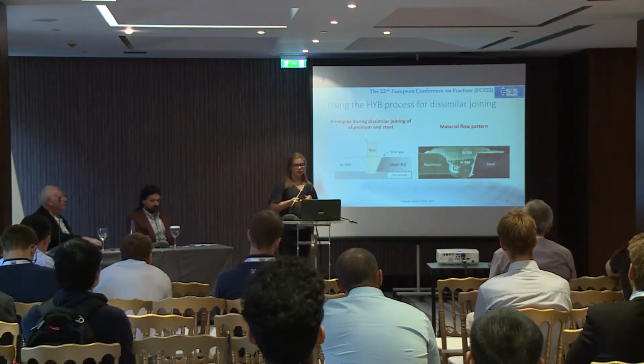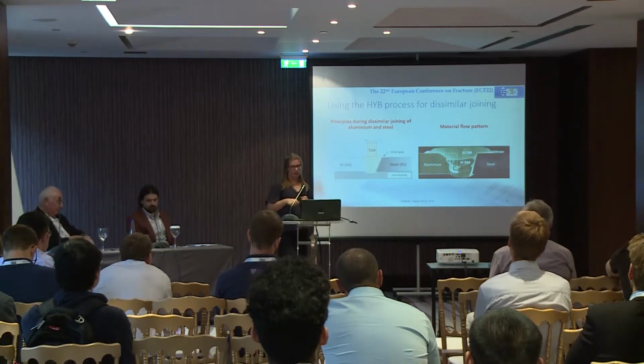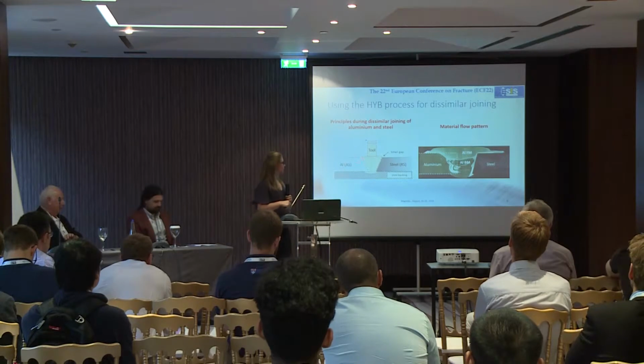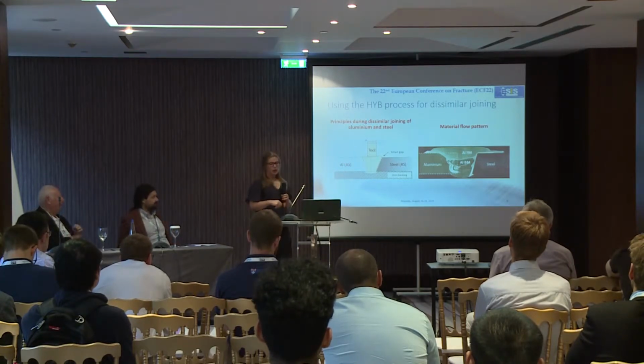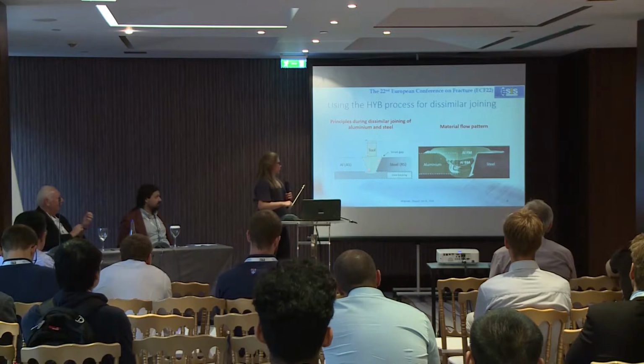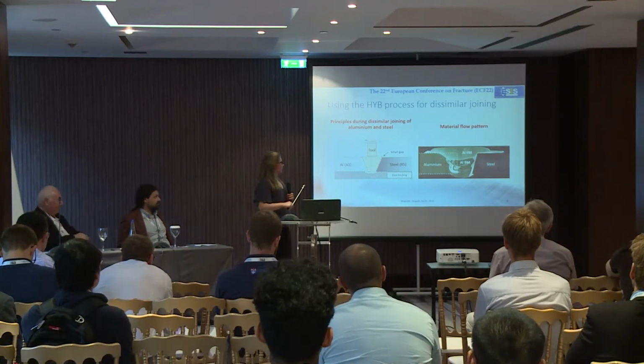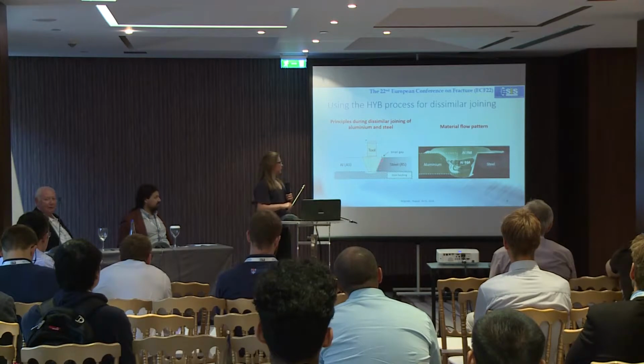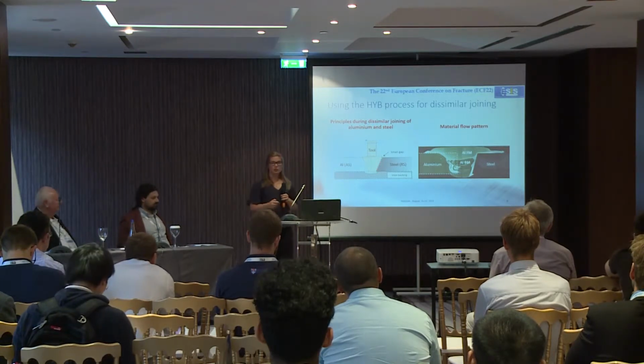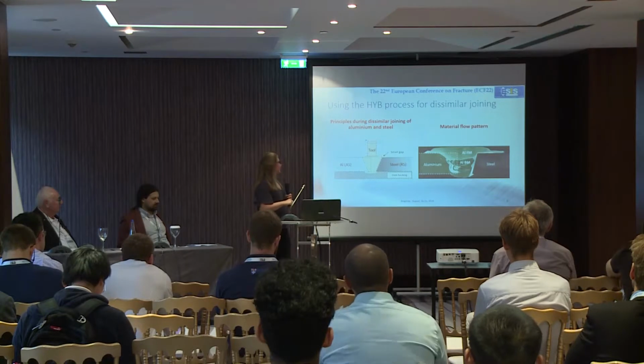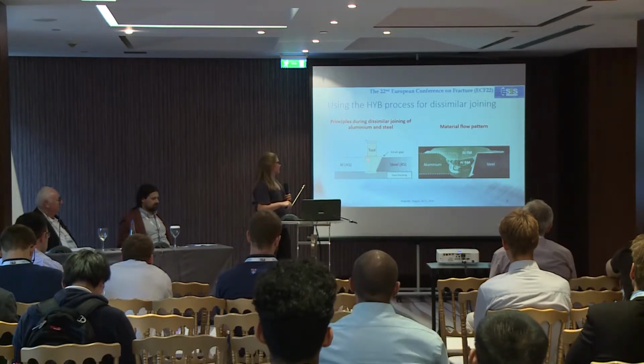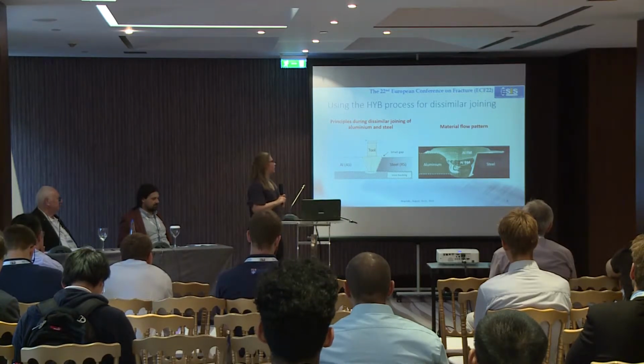So in a real joining situation, the extruder head is clamped against the 2 plates to be joined, as you can see here. And they are separated from each other with a groove. Note that the steel side is machined to form a slope. This is to ensure that the tool is not in contact with the steel. And on the aluminum side, the pin is slightly larger than the groove, and this is to ensure contact between the tool and the aluminum base material.